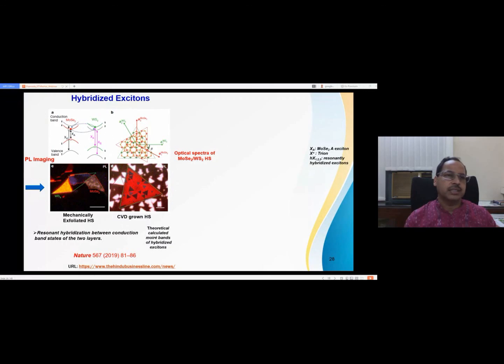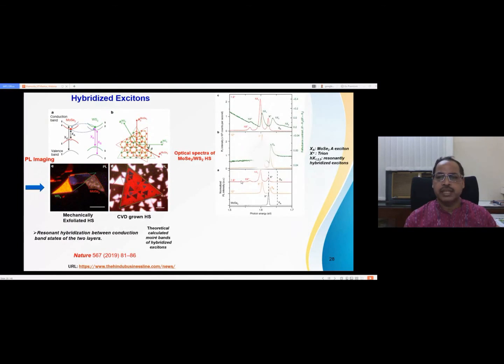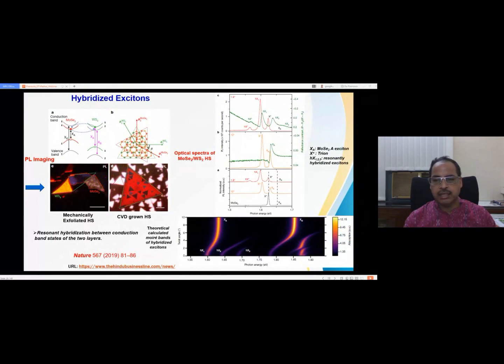So this is another heterostructure, this MoSe2 and WS2 heterostructure. When the conduction band energy levels are more or less the same, band hybridization takes place. And then there is a split in the energy level of this hybridized band, and we can get different types of hybridized excitonic features. So we have done theoretical as well as experimental validation. You can see, in comparison to the normal A and B excitons, other types of excitons, HX1, HX2, the hybridized excitons, and that has been reflected in our experimental plots of PL as well as the reflection contrast spectra. These are X1, HX1, HX2, and other things. And this was highlighted in the Hindu Business Line.